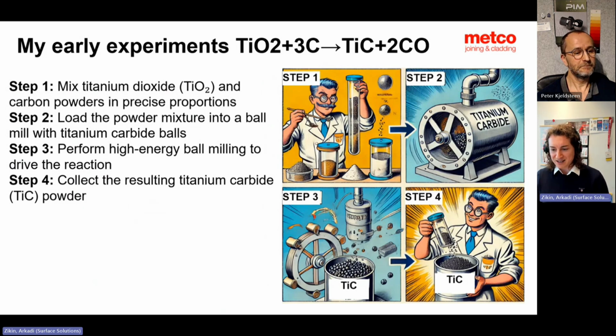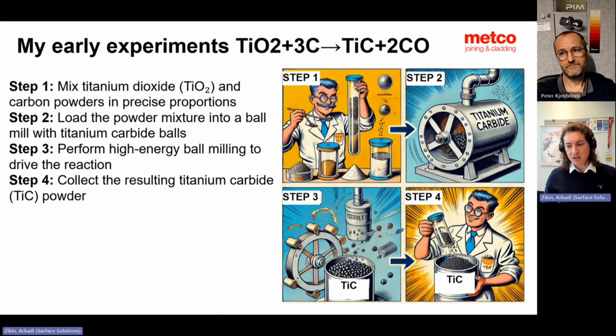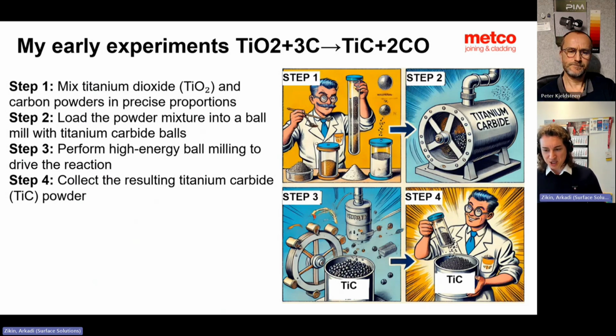process seriously. As a young, ambitious person, I started to work on titanium carbide because it has lower density compared to tungsten carbide. It's easy to get, but titanium carbide is also not the cheapest material on the market. Nowadays, we talk about laser cladding, brake disc applications. Titanium carbide is almost a standard choice by the companies to do it. When I was young, 15, 20 years ago, as a young student, it was not the case. And we were looking at titanium dioxide because it's an extremely cheap and widely available material.